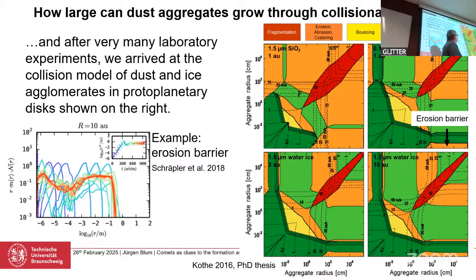So I'll explain what you're seeing here on the x-axis. It's the size of an aggregate growing from microns in the lower left corner to possibly large sizes. On the y-axis, the same axis. So two particles come together at the speeds indicated at the contours in meters per second. So 1 meter per second would be that. Here's 1 meter per second. 10 meters per second is here. And the four panels indicate different grain sizes and different grain materials.